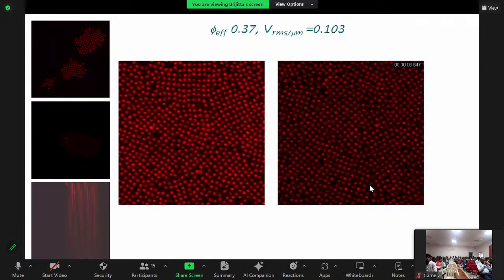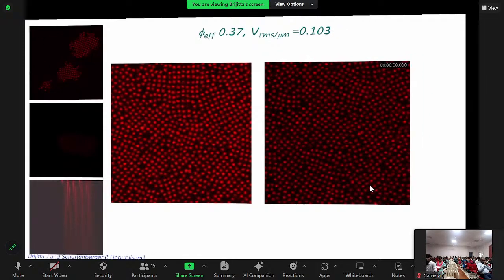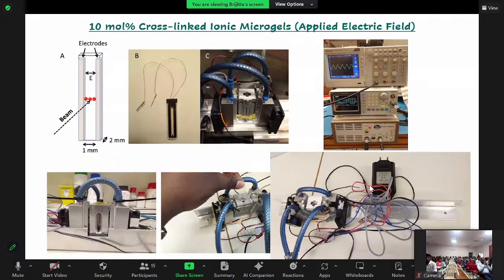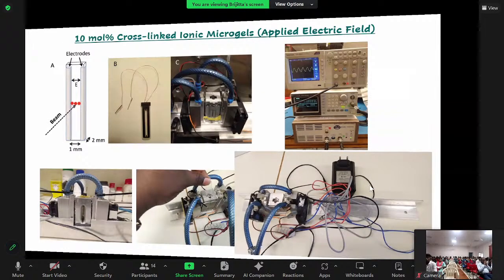Next, what we saw so far was larger size spheres, so we used a microscope. Now we will have very small particles. I synthesized particles of around 70 nanometers to 100 nanometers. For this particular experiment, I used 100 nanometer particles and put them in a field cell, which we constructed for our neutron scattering experiment. These experiments were conducted at the FRM2 KWS2 small angle neutron scattering facility in Germany.